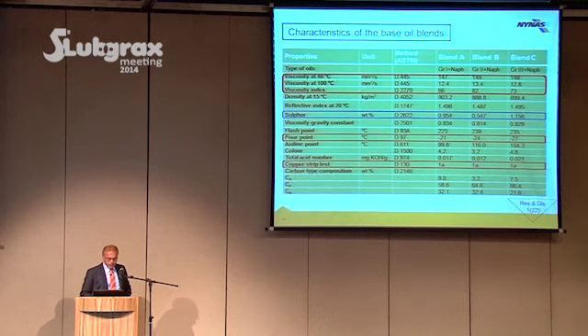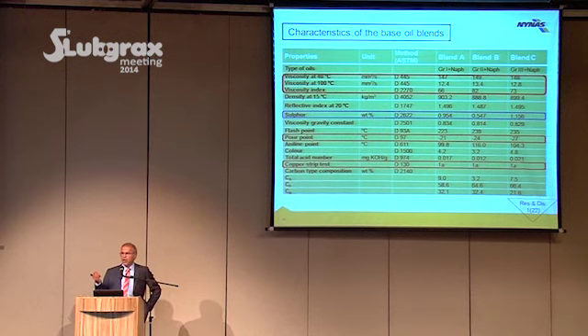Okay, copper strip. I mentioned that we have had high sulfur content in the oils, and it was a risk for negative impact on the copper test. And we can see here that we got the best rate.